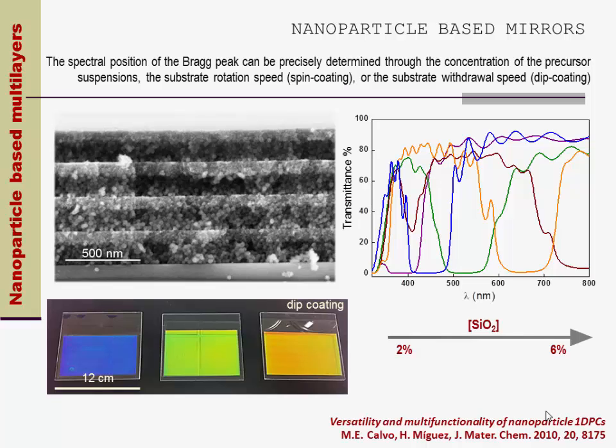What we did was to develop mirrors that were very robust optically, meaning that they can have very high reflectance, and also chemically and thermally, and that substitute the diffuse scattering layer that is commonly employed to get this boost in efficiency that is needed in the field.